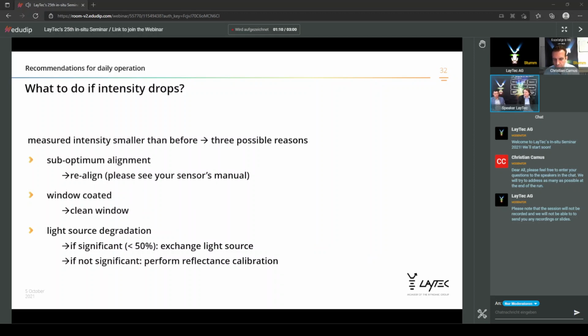Heiko was just agreeing that dry cleaning is also possible. It depends on the amount of coating. Sometimes even cleaning it with a Q-tip with IPA might be sufficient. Depends. And as mentioned, if the light source degradation is really significant, that means, and this is also mentioned in your calibration protocol, less than 50% of the initial intensity, we strongly recommend to start to exchange the light source, contact LayTec or contact Aixtron. If you are still able to work, this is the right time to start to get the replacement part.